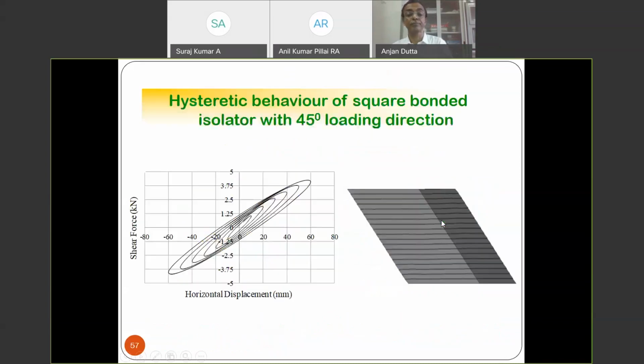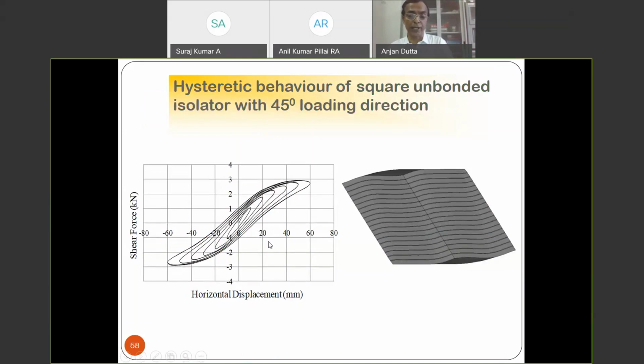Right? And then we have carried out a detailed numerical study with different directions of loading: loading which is parallel to the direction of fiber, normal to the direction of fiber, 45 degrees to the direction of fiber, and we have found out the corresponding load displacement curve for both bonded and unbonded types. And when I say bonded, that means they are connected to the superstructure and substructure. Unbonded, it undergoes a rollover deformation like this. And you can see for the unbonded, you have the initial stiffness, and then there is some reduction in the stiffness, but nowhere is it negative stiffness.